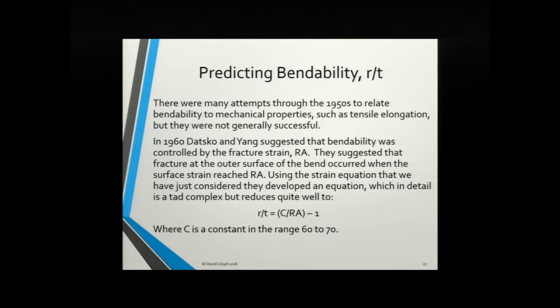We would like to be able to predict bendability. There were a lot of attempts through the 50s and whatever to predict bendability, but Datsko and Yang in 1960 suggested that bendability was controlled by the fracture strain of the material, and once the strain at the bend surface reached that fracture strain, you get cracking, and that would allow you then to develop an equation to predict it. And they used the Sachs equation in their paper, which, if you can get hold of, it looks at a static neutral axis and a moving neutral axis, and the form of the equation for both is exactly the same. It's of this sort of form, which is really very simple.